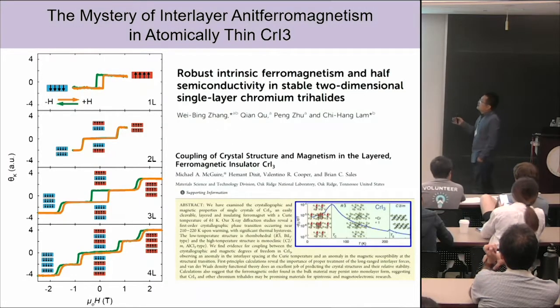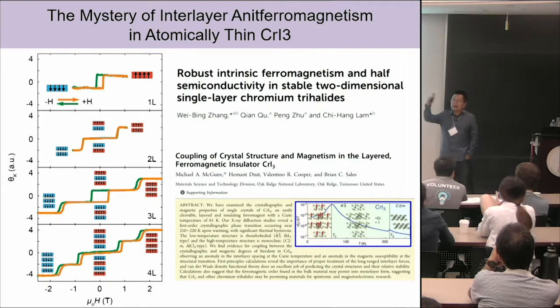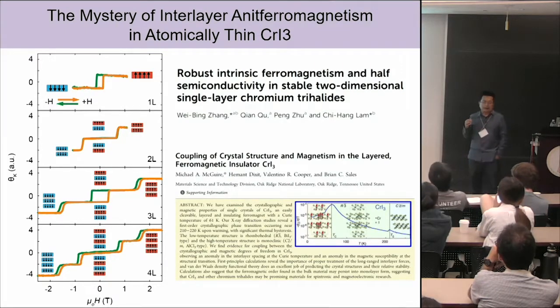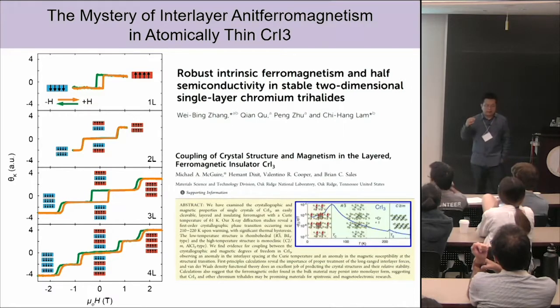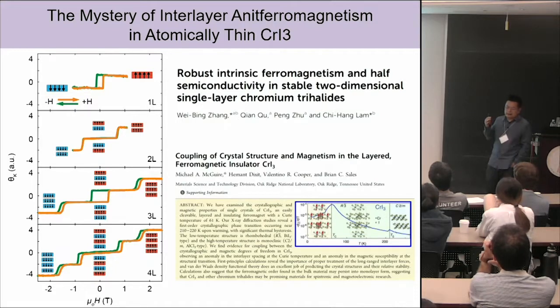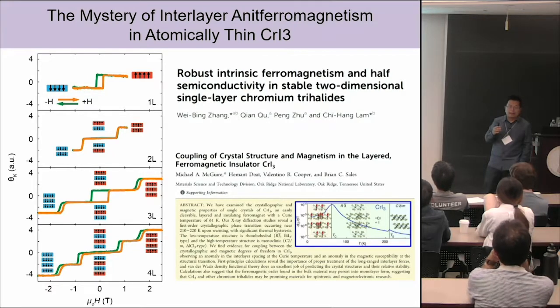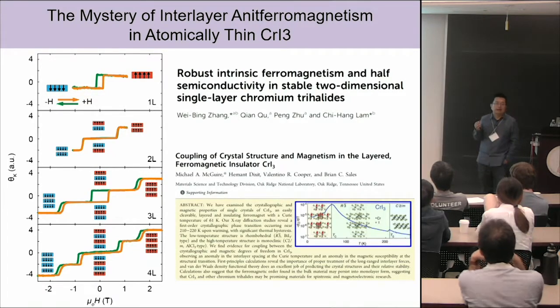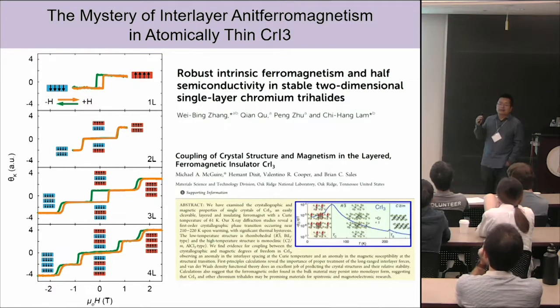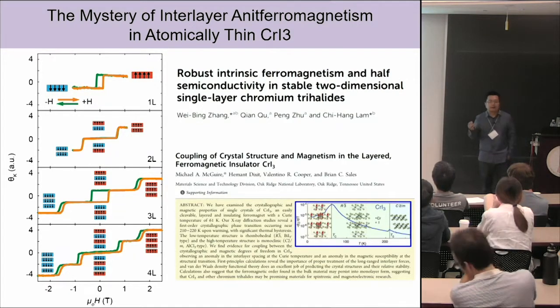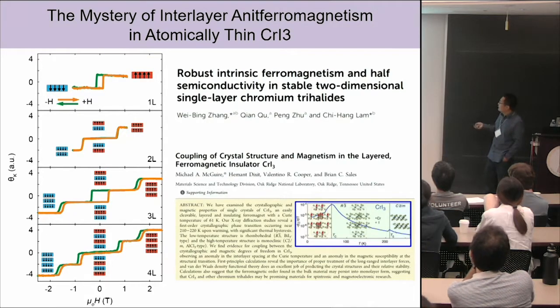There's actually a mystery in this interlayer antiferromagnetism. I was puzzled at the beginning by these interlayer antiferromagnetic couplings, because before our work there were already theoretical calculations on these crystals, and what they show is that the crystal CrI3 itself should be ferromagnetic from bulk crystal all the way to monolayers. But clearly, my experiment shows that the atomically thin limit is antiferromagnetically coupled. So what's going on there? And my collaborator's bulk crystal measurement also shows it's ferromagnetic.